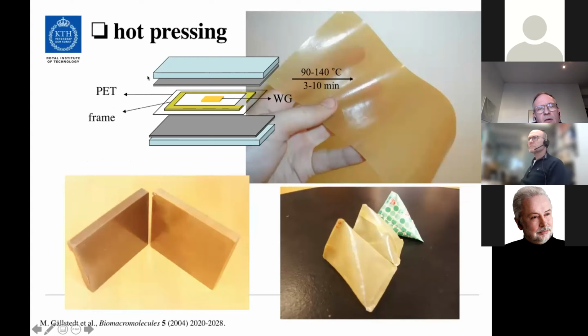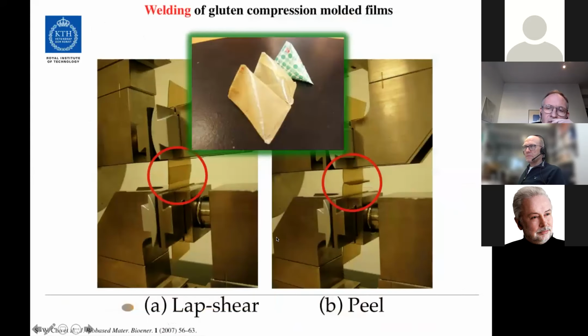Hot pressing or compression molding is probably the best technique for this material. And here are some examples of that. You see the film again. Here are 2 centimeter thick plates, compression molded. And here are actually packagings we made. So you have to be able to weld the material. And if you add a plasticizer to it, you can weld it very well, as illustrated here.